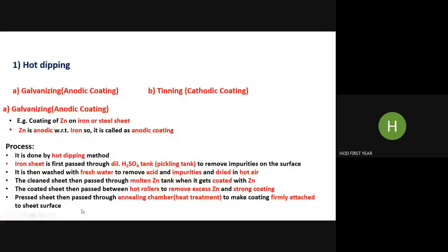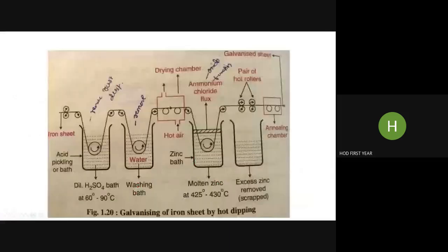Okay, so let us see this flow chart. If you look at the flow chart, you may understand. Sometimes they ask to describe the galvanizing process with the help of a flow chart. So here you will understand. First step is preparation of surface. These 3 steps, 1, 2, and 3, are preparation of the metal surface to remove impurity. If we take the example of an iron sheet to be coated with zinc, first is acid treatment. The sheet is allowed to pass into a sulfuric acid bath, dilute sulfuric acid at approximately 90 degrees Celsius. So all impurities are then removed.